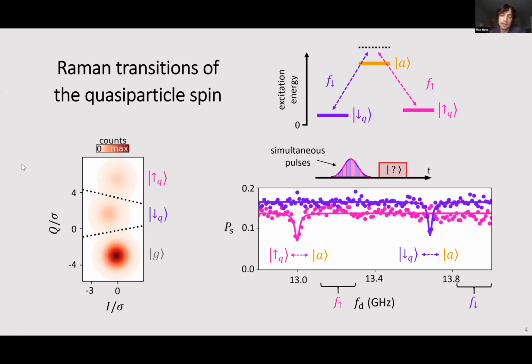So what we do instead is we start all of our Raman experiments with one measurement pulse that we then post-select on being in the up state. In this way, we can imagine pretty much starting with the quasi-particle in the spin up state. Then we apply a Raman pulse, and finally we check the final state of the system.